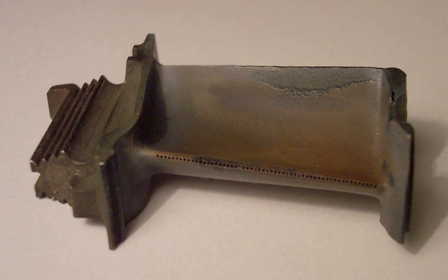Alloying elements that are commonly found in these superalloys include Al, B, C, Co, Cr, Mo, Ni, Nb, Ti, W, and Y. While Al is introduced for its oxidation benefits, Al additions must be kept at low weight percent (wt%) because Al stabilizes a ferritic (BCC) primary phase matrix, which is an undesirable phase in superalloy microstructures, as it is inferior to the high temperature strength exhibited by an austenitic (FCC) primary phase matrix (gamma).